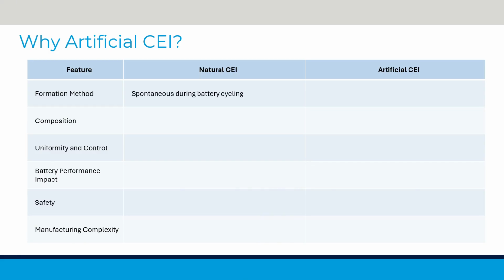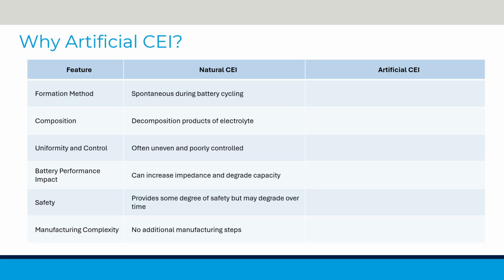The natural CEI forms spontaneously on the cathode surface when the battery undergoes repeated charging and discharging cycles. The electrolyte breaks down at high voltages, releasing byproducts that accumulate and eventually form a passivating layer on the cathode. The uncontrolled formation of the natural CEI often leads to non-uniform and unstable layers that may not effectively protect the cathode from further reactions. This contributes to performance degradation, increased impedance, and capacity fade over time.